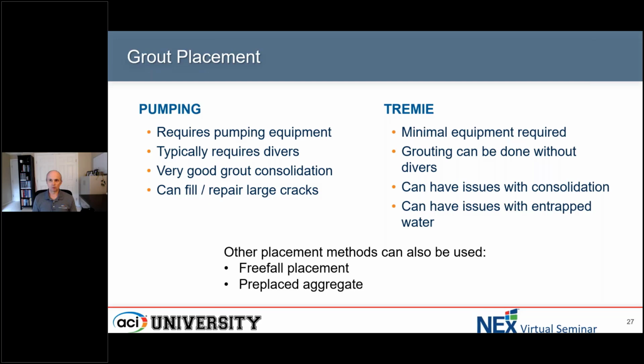Okay, then in terms of grout placement, again, I showed grout being pumped, which is the best way to get grout placed with very good consolidation and very good grout penetration behind the annulus. Pumping, however, is relatively complicated. It does involve pumping equipment, and usually requires divers that go down to actually attach grouting hoses to the jacket as the grout is being placed. So it is much more complicated from that standpoint.